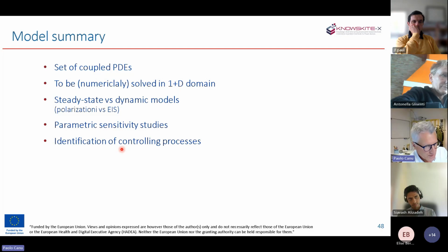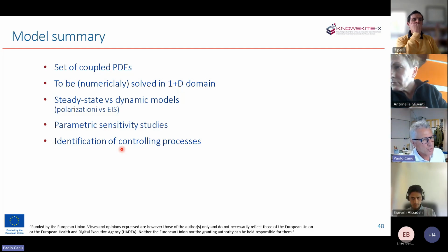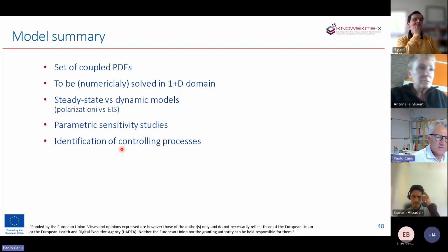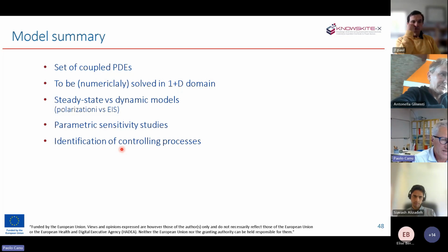Another important feature is a steady-state simulation or a dynamic simulation, where the steady state is useful to predict polarization curves, while the dynamic, more sophisticated implementation of the model allows you also to describe transients that are typical of an experiment like impedance spectroscopy, where there is a perturbation of the applied voltage just to sample how the experimental cell is changing the impedance at different frequencies.